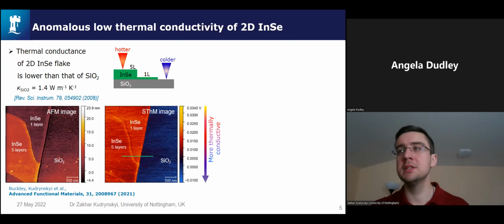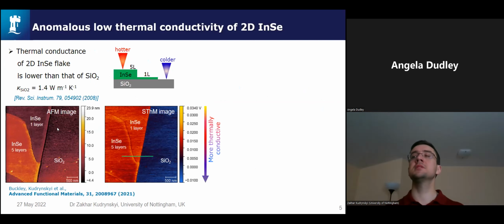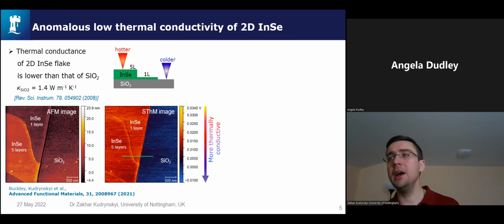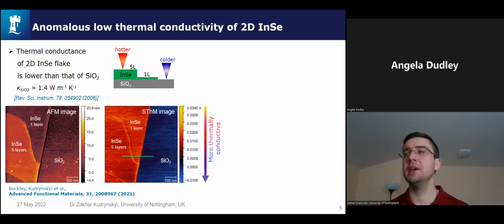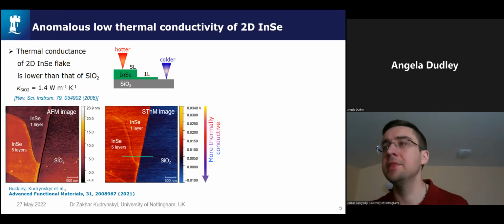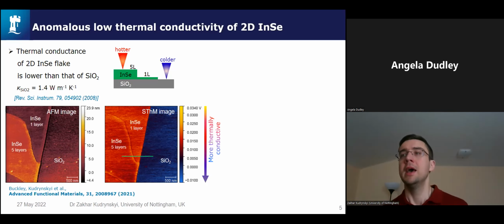So here on the left, you can see an AFM image of an exfoliated indium selenide flake on a silicon dioxide substrate, consisting of two parts, 5 layers and 1 layer. On the right, you can see a corresponding thermal image. It shows that when the heated tip touches the silicon dioxide region, it gets much colder because silicon dioxide is thermally conductive, and thus it dissipates heat from the tip. In contrast, when the tip moves to indium selenide, it remains relatively hot, which indicates that the flake does not conduct heat well. As a result, in the thermal map shown here, both parts of the indium selenide flake appear red-orange, indicating that the ability of indium selenide to dissipate heat from the SThM tip is lower than that of the dark blue colored silicon dioxide.